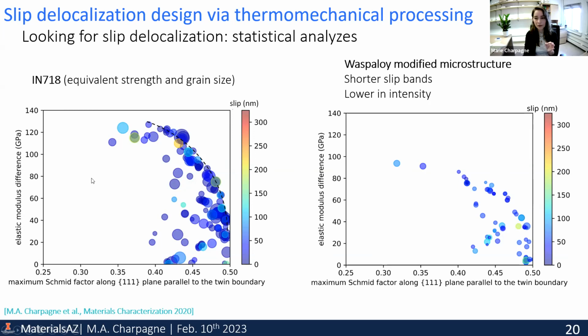So looking at this, with our modified thermomechanical treatment, we actually want smaller markers and less intense in terms of color scheme. And we indeed have lesser markers. This is a similar area. We had similar amounts or similar density of annealing twins that were prone to forming these slip bands. And we see that indeed we have much smaller markers and also smaller intensity. And of course, the ones that are with high difference in elastic modulus are somewhat still there, but I want to say that they are much less intense. So this is good news for the efficacy of our process. And here you can see that we have, in general, smaller and less intense slip bands near these twin boundaries. So this is a good hint towards the potential success of this approach.